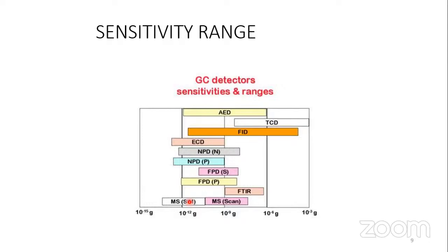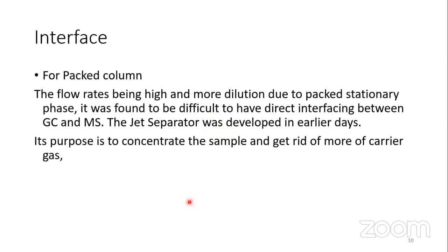A GC has to be connected to MS. So we require some kind of interface between GC and MS. GC works at slightly above atmospheric pressure. MS requires a very high vacuum. So you are trying to combine two instruments, one which works at a little higher pressure than atmospheric pressure, the other works at the level of 10⁻⁵ millimeter of pressure, very much less than the atmospheric pressure. Atmospheric pressure is 760 millimeter and we are working at 10⁻⁵ millimeter. Okay, so we have to combine these two systems. So we require some kind of an interface between the two.